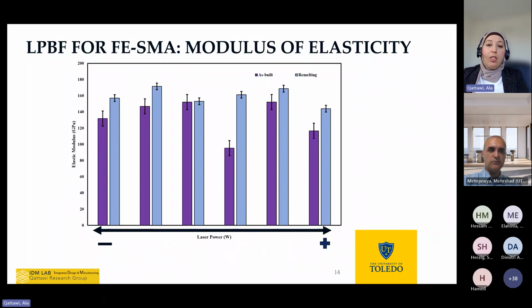You can see, for example, at certain laser powers, what you can achieve in the as-built state. Basically, one laser pass manufacturing the material will achieve low elasticity and high hardness, and the material is brittle, so we cannot even get it out of the building plate in one piece. But with remelting for each layer, that can be improved, and we saw a significant improvement in the modulus of elasticity and technically the hardness, reducing the brittleness of the material.